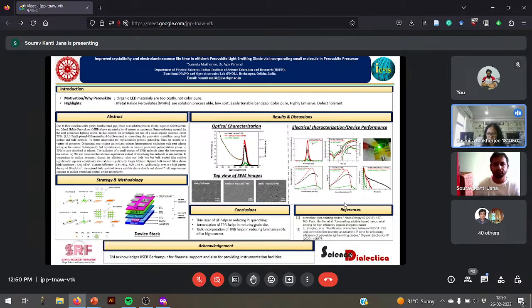If we want a perovskite LED, a perovskite phone after 20 years in our hand, we should make it stable. For that, I chose an electron transport layer called TPBI. I incorporate this material into the perovskite precursor. Precursor means perovskite salt and solvent mixture. In the strategy and methodology, you can see, I use 2 different ways. One is surface treatment, another one is bulk treatment. Surface treatment means on top, I coated a thin film of perovskite, and on top of that, I use TPBI doped anti-solvent solution. And another is bulk treatment, where in the precursor itself, I doped this TPBI.